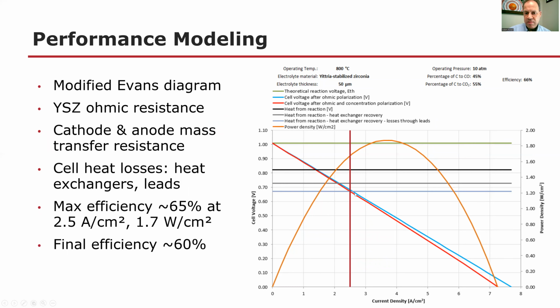So we have to run at least 2.5 amps per square centimeter here, anything above that. And at that, we're running at about 65% efficiency at 2.5 amps per square centimeter and 1.7 watts per square centimeter. So our final efficiency would be somewhere around probably about 60%, which compares very favorably with the 30% that we run at for either the integrated gasification combined cycle or the chemically mitigated metal oxide cell cycle we saw earlier today.